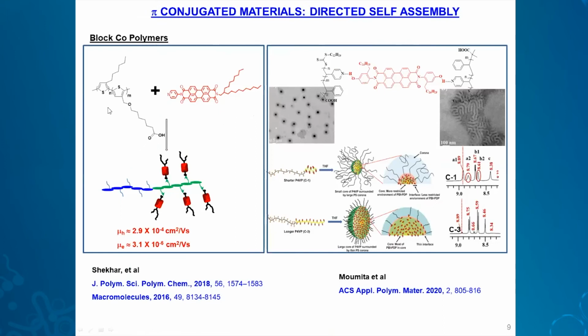The self-assembly we also took to donor-acceptor type self-assembly. In the previous example, where the P4VP was an insulating polymer, we have now used a donor polymer, which is a polythiophene. This is a block polymer. One block has this hexyl chain here, whereas the other block has a carboxyl terminal unit, with which this perylene molecule was self-assembled, again schematically shown like this. So now here it exhibits both the hole and electron transportability.